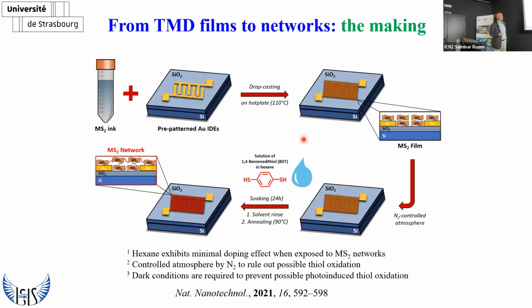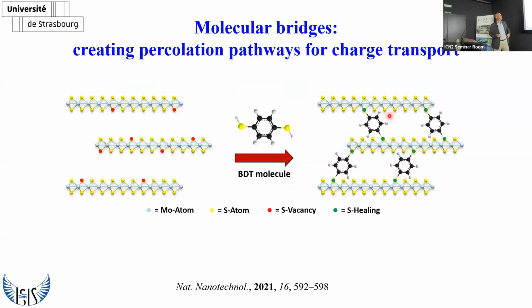And then we drop cast a solution in hexane of our benzene dithiol. We chose hexane because it exhibits a minimal doping effect on the MoS2. And then we did this in a controlled atmosphere to avoid photooxidation, and actually in the dark as well. And this is what I call network. So this is network, and those up here are the films. Now, the network is what we have on the left, with the sulfur vacancies or defects used as anchoring sites to create the network of these nanosheets.